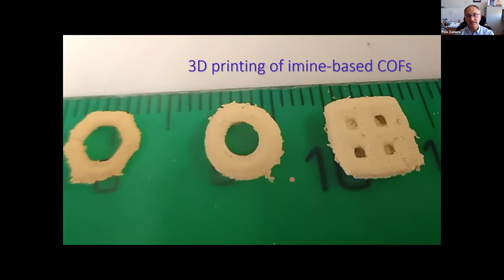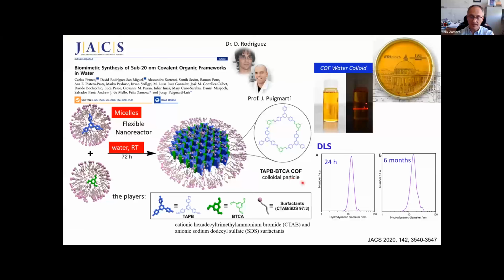And in order to do that, we started with work that we previously carried out in collaboration with Professor Josep Puig Martí from Universitat de Barcelona, in which we observed that we can form nanoparticles of COFs and MOFs using this simple reaction in water at room temperature, using a kind of flexible nanoreactor based on micelles that we form using a combination of these two surfactants, CTAB and SDS.